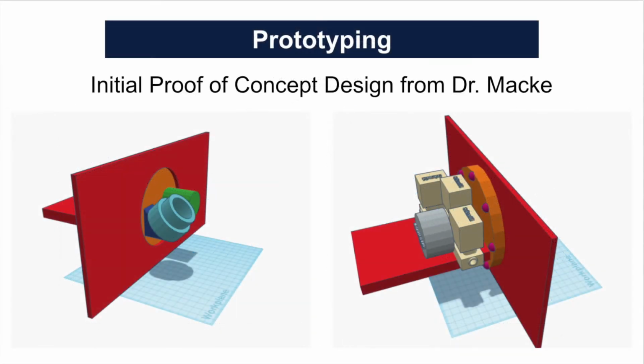Many design considerations had to be accounted for in the design of this apparatus. Primarily, material requirements must be met, meaning no lubricants or non-approved metals or plastics could be used. This presented a unique challenge to design a device that was well sealing without the use of those materials. Shearing metal-to-metal contact was also to be avoided in order to mitigate the possibility of particles abrading and potentially contaminating the sample. Finally, the closure needed to be repeatable, meaning the volume of the chamber did not change with opening and closing of the apparatus.